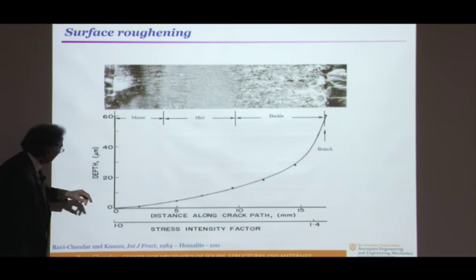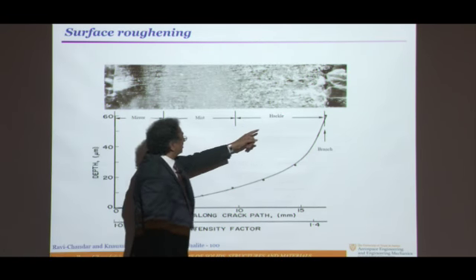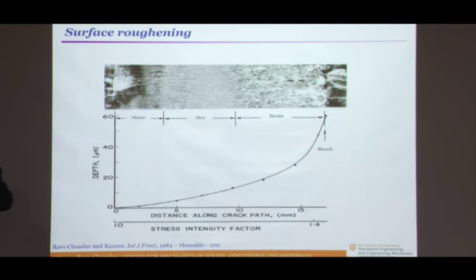So in addition to the branching there, I noticed from the top and the bottom something happening. Nucleation. And this happens in real materials in the examples. This is actually recreating an experiment we've conducted. So there is a wave that comes from here and it reflects. There are waves from the corners that come around here. Many times they reinforce. And because phase field models are able to nucleate cracks, you see such nucleation.